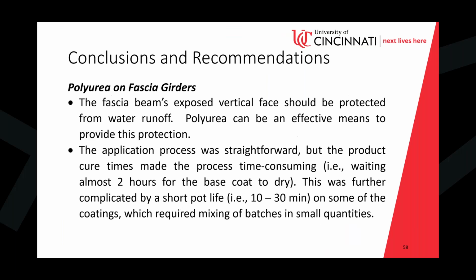With the polyurea, the fascia beam's exposed vertical surface should be protected from water runoff, and the polyurea can be an effective means to provide this protection. The application process was straightforward, but the cure times were time-consuming, and then the pot life made it challenging, requiring mixing of batches in small quantities.